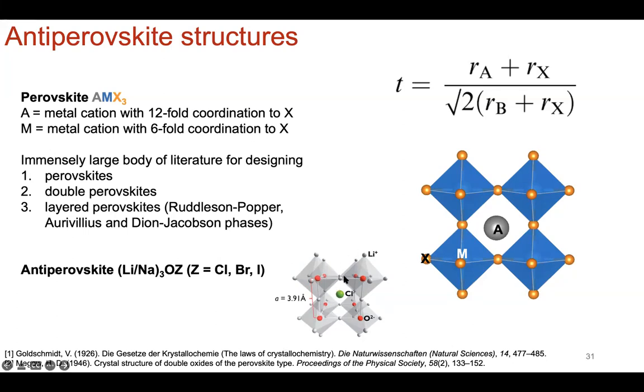The oxygen are shown here, and then the lithium or sodium cations are actually at the corners of the octahedra. So it just flips where the cation and where the anions are. Okay, so they are related, as you can tell, but where you would expect the cation and the anion is different. You would expect X3, but here it's Li3,